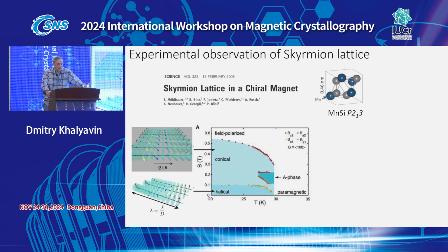So this material is a non-centrosymmetric cubic ferromagnet, exactly like in the theoretical work by Bogdanov and Yablonsky. The ground state in zero field of these materials is a long period helical structure imposed by this non-centrosymmetric nature of the crystal structure, because non-centrosymmetric means that Dzyaloshinskii-Moriya antisymmetric exchange is active there, and competition between antisymmetric and symmetric exchange imposes these long period helices.